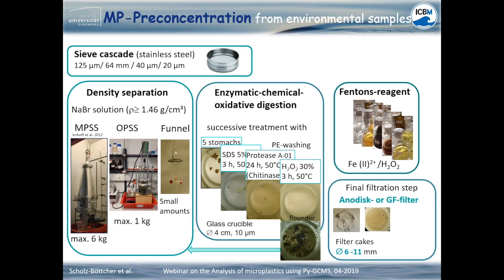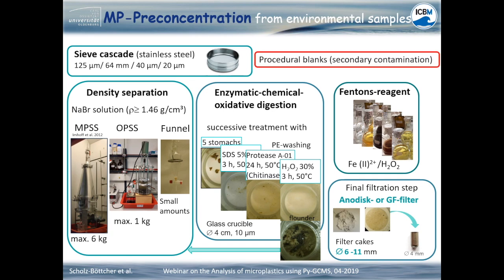At the end, the whole sample residue is filtered on an anodisc or glass fiber filter of a very small diameter that is directly placed into the pyrolysis cup. Obligate to evaluate the data quality is to run a consequent procedure blank along the whole sampling and cleanup process due to an immense risk of secondary contamination.